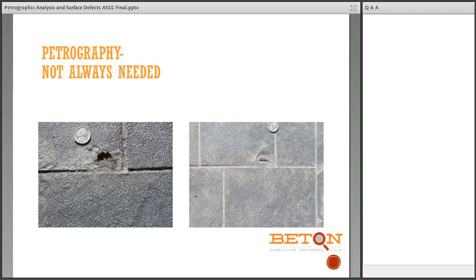Initially got called out to look at this for a pop-out issue. And generally around here in Minnesota, you think of pop-outs being due to alkali silica reactive aggregates like opal and shales. I got out there and I could see that this was in a pattern, and it always happened in the same area. In the stamps, it was a stamped concrete, and we always saw it in that same corner, and then you come to where it stops, and then you see the offending material that was stuck on the bottom side of the stamp. So that really, you don't need to take core, you kind of know what happened there.